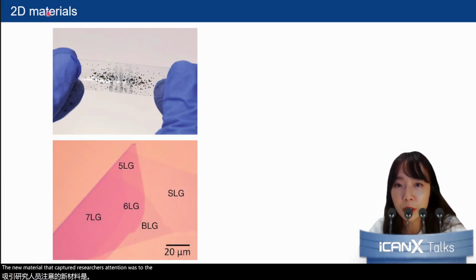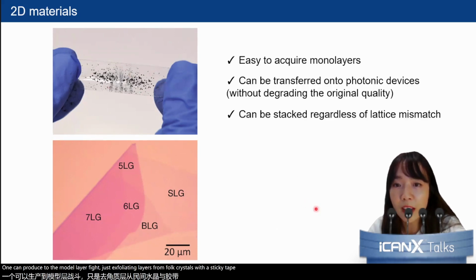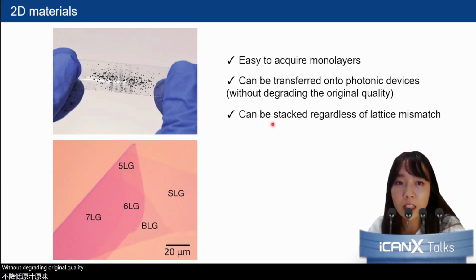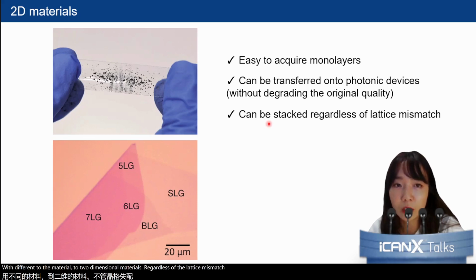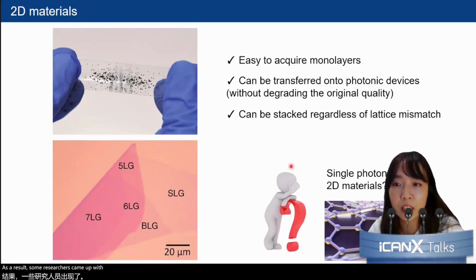The new material that captured researchers' attention was 2D materials. What made them prevalent in the lab was the easy fabrication method to get monolayer samples. One can produce a 2D monolayer by just exfoliating layers from bulk crystals with sticky tape. Apart from that, due to its atomically thin nature, it can be transferred to various photonic devices without degrading the original quality. Additionally, heterostructures are possible with different two-dimensional materials, regardless of the lattice mismatch. As a result, some researchers came up with the idea of creating a single photon emitter from 2D materials.